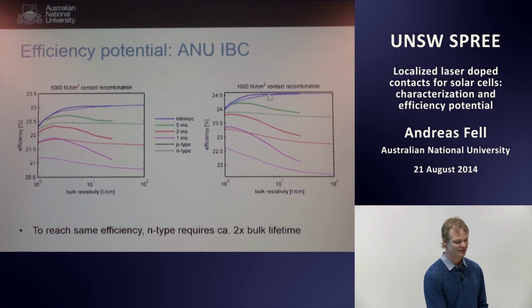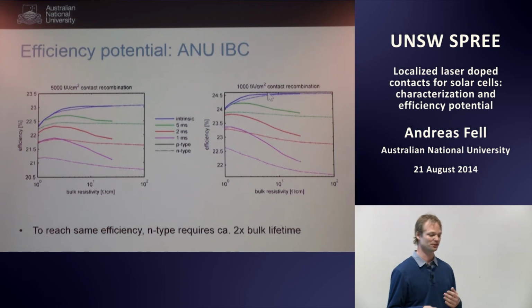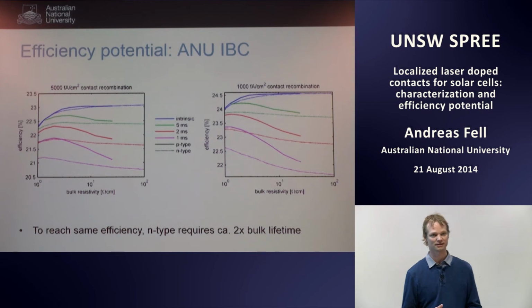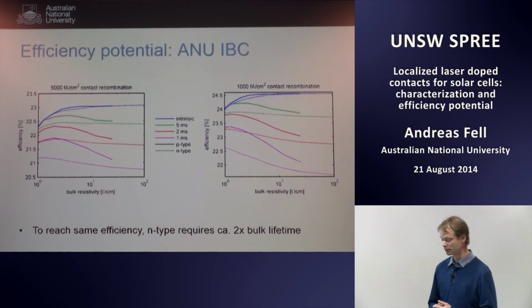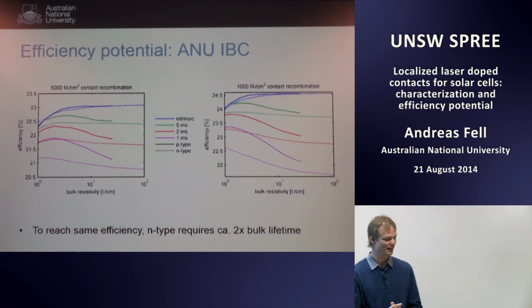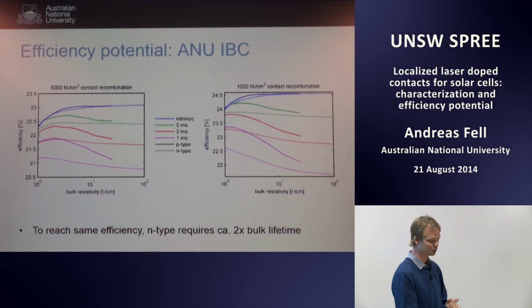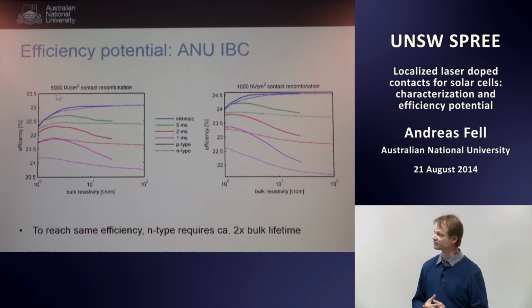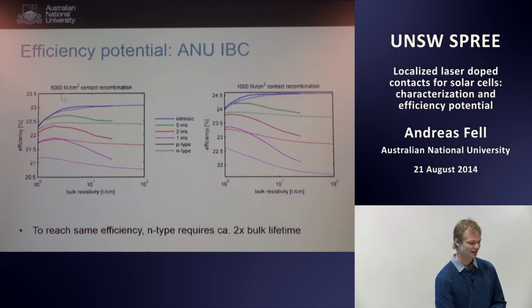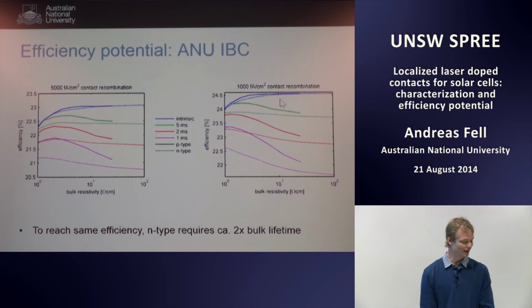So this is very optimistic. This is what you ideally get for a contacted, highly doped region. It could be even a bit lower for a properly doped region, but I think if you would get 1,000 femtoamps with a laser, we would be very happy. And this might be more the realistic thing. So definitely with the two-step process, this should be feasible. So I would call this a realistic and this an optimistic scenario. And there are a couple of interesting things to see.